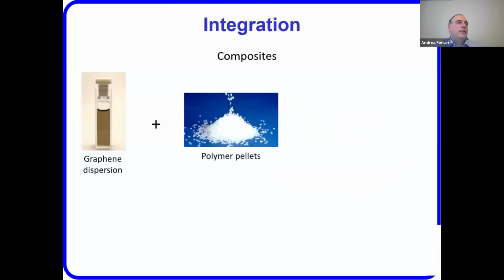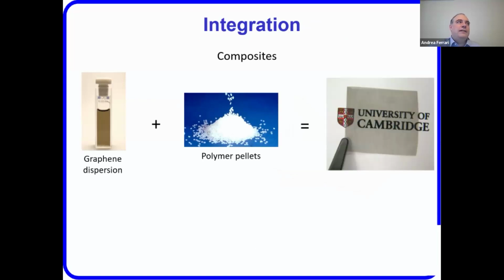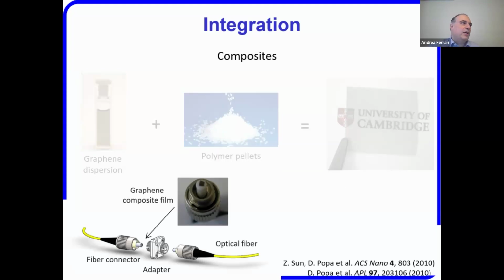So let's consider liquid phase exfoliation. You create a graphene dispersion, then you use some polymer and create a composite. Bear in mind, this composite is built for optical properties, not as a mechanical composite. You don't need a big grafting, you don't need oxidation or anchoring sites for the graphene. Graphene only has to sit there in order to be inserted in an optical fiber.